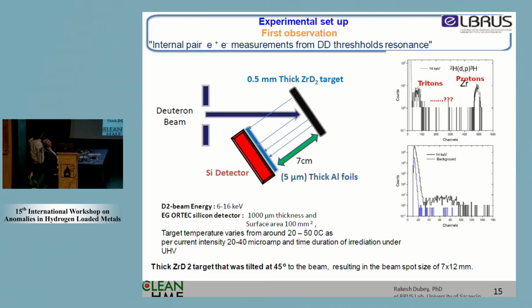So this was our experimental setup, where we bombarded a deuterium beam with energy of 6 to 16 keV, and the target was 0.5 mm thick. First we took a slightly thicker detector with a thickness of 1 mm, and the surface area was about 100 mm square, and the target temperature was around 20 to 50 degrees centigrade, depending on the current intensity. We put the aluminum foil for two reasons. First is to protect the detector from scattered deuterium beams, and second is to filter the clean events with respect to other charged particles like helium-3 and triton.